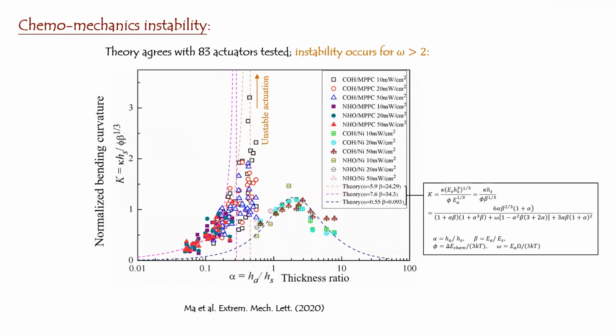In terms of the fabrication side, there is a constraint too, because these are not really good electrical conductors, so we cannot grow them too thick. A few microns, 10 microns would be like the limit, of course, depending on material. But we are also thinking ways of upscaling the whole thing. So we cannot get away with the coating configuration. So the material has got to be coated on something, but that something may not be a flat layer, right? It could be some fabric, some cotton, some sponge. So we are working hard along that direction. One day we may be able to achieve a 3-dimensional construct that can dance, jump up and down.